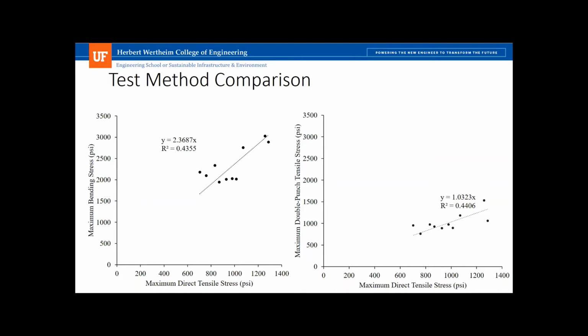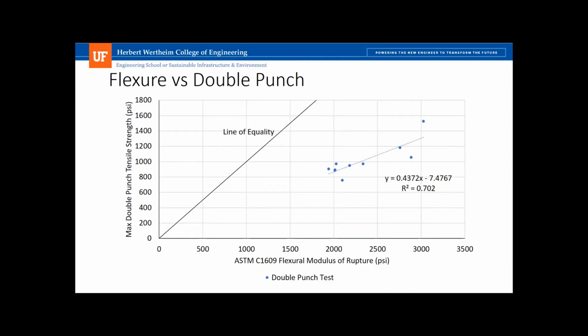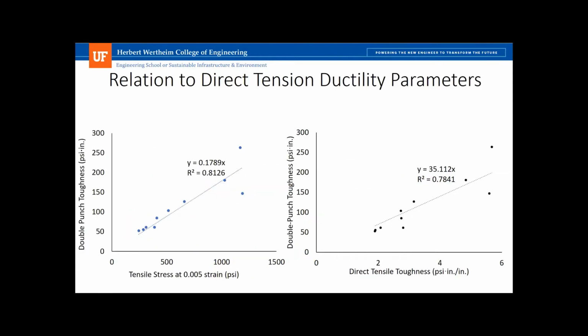So something to be aware of. We find that when we compare the flexural modulus of rupture with the double punch test tensile strength, you get very nice correlations. Again, you just have to be aware of that increase because of the flexural modulus of rupture. When we look at direct tension ductility parameters, so we compare, say, the tensile stress at 0.005 strain or the direct tensile toughness, we get, again, excellent correlations.